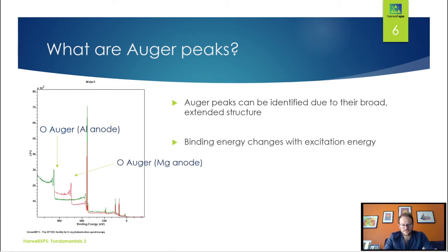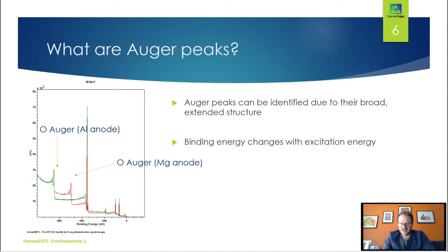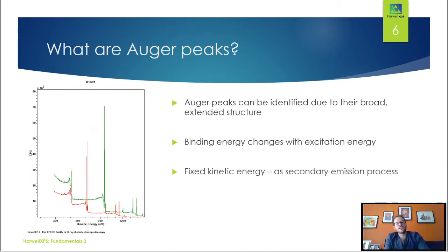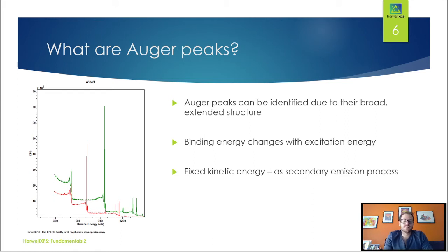One way to identify Auger peaks is by that broader structure, but another way is that they change apparent binding energy when you change the excitation energy. We're not actually changing the binding energy of anything — what's happening is that Auger peaks have a fixed kinetic energy. If you remember from the photoelectric effect, changing the incoming energy changes the kinetic energy of photoelectrons, but Auger peaks have a fixed kinetic energy regardless of what excitation energy you use, as long as it's sufficient to begin the process.